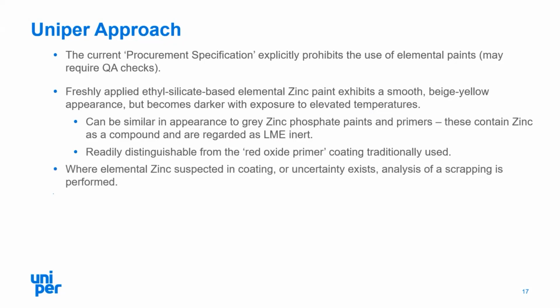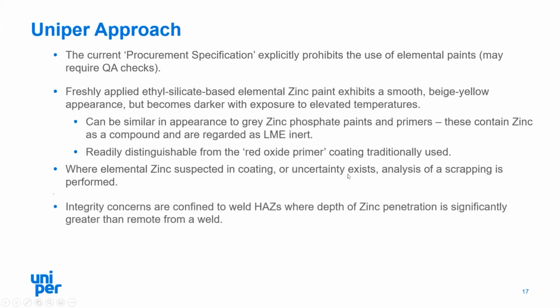Where there's any uncertainty with regard to the nature of the coating which is on the surface with regard to elemental zinc, then analysis of scraping should be performed to better understand exactly what you're dealing with. And it's also significant to note that the integrity concerns we're talking about here are confined to the weld heat affected zones. This is where the zinc penetration is significantly greater than remote from the weld. Effectively, operating temperatures do not encourage the infusion which we're talking about for most of this presentation. The events which we're talking about here are associated exclusively with those high temperatures up above 800 degrees centigrade, which we've seen during the welding process.